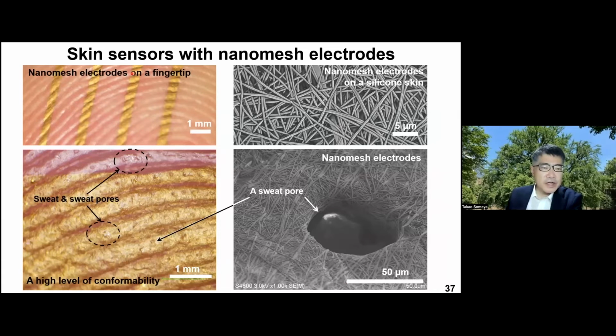So this is the nanomesh electrode put on the fingertip, and the shining parts are gold. That looks like a continuous gold film. But if we magnify the gold layer by SEM, it has a porous structure. This is the magnified image. This is the gold region and the non-covered region, and the dark spots are sweat pores.